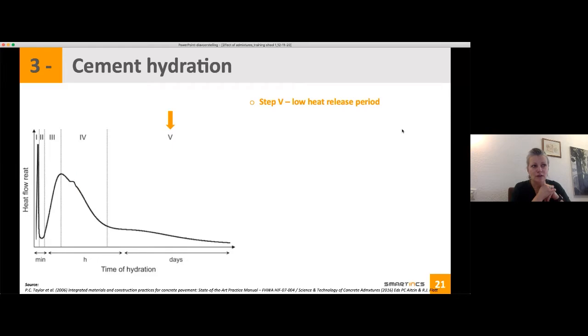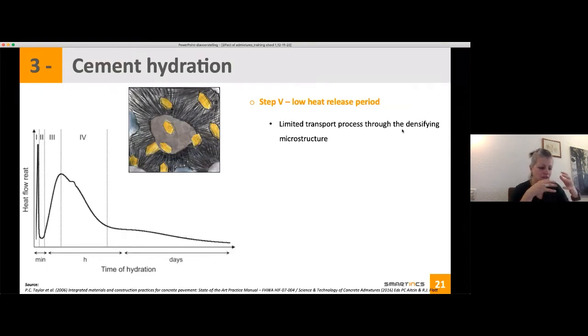Then you have step 5, and step 5 is a quite slow, quiet heat release. And this is because you have formed already a lot of hydrates. So if you still want, from the inside of your cement particles, to dissolve and to still form some hydrate, it needs much more time to reach the place to precipitate.